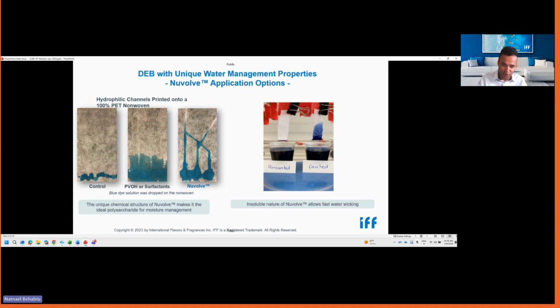The one thing is that polyester or polyolefin, which you use, for example, in an ADL for a diaper, are not hydrophilic, right? And so a lot of the time, this material needs to be treated to improve the hydrophilicity. The treatment can often be an acrylic petro-based treatment, can be PVOH, can be surfactant. What we are showing here is that if we treat these hydrophobic woven and non-woven structures with these DEB polysaccharides that are, in this alpha-1,3 version, water insoluble, so this is really a permanent treatment that we can apply, then we can really design the wicking and water management behavior of this final structure. And this is just a couple of examples of how we can, literally, print channels as well as significantly change the wicking behavior of a structure that is fairly hydrophobic to begin with.